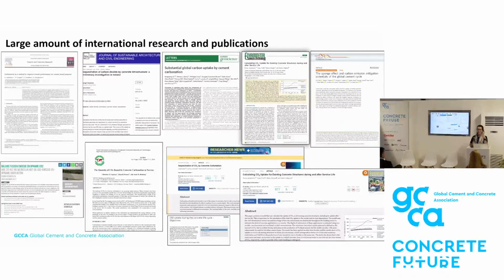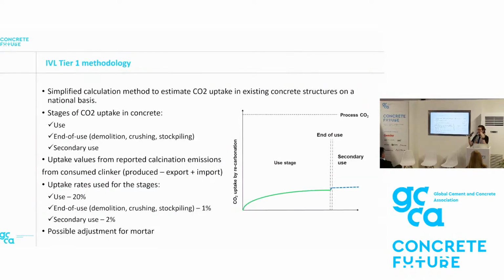And IVL has therefore worked on the basis of established research, looked at all that was available, of course the reference in the IPCC document, the standard that was existing with the PCR, the product category rule for cement and concrete, and has developed, fully in line with IPCC methodology, a 3-tier methodology. I guess many of you are familiar with IPCC ways of quantifying emissions and removals. If you don't have much information, you go for a tier 1 assessment, which is a very conservative assessment. If you are quantifying emissions, you would probably tend to overestimate the emission with a tier 1 methodology. If you are quantifying removals with a tier 1 methodology, you would underestimate the removals. So this is the conservative way.